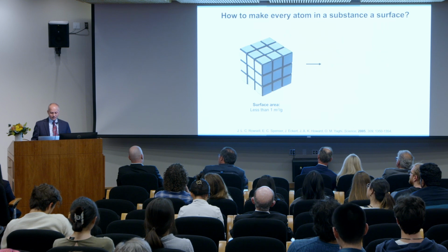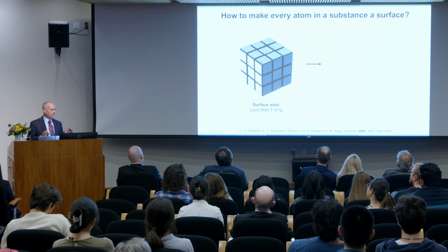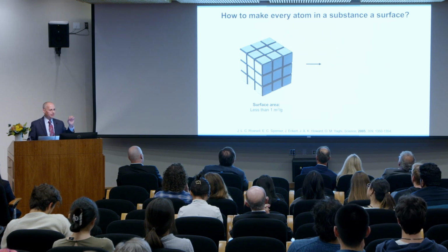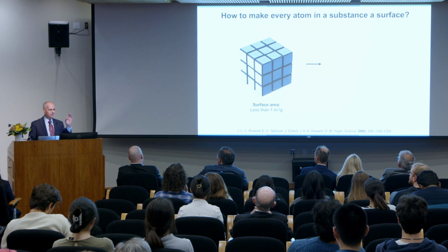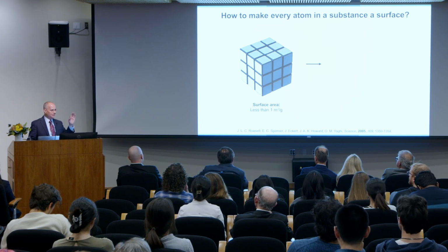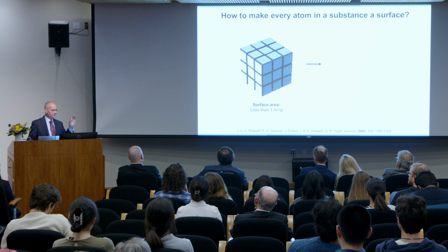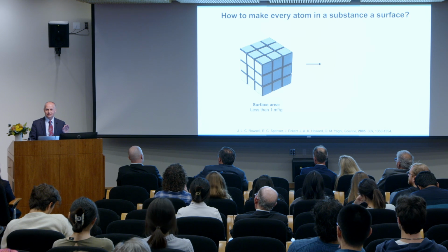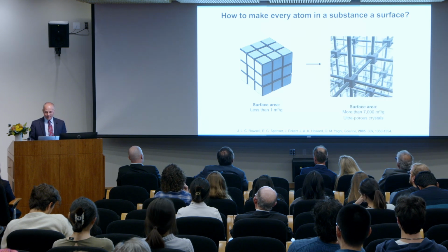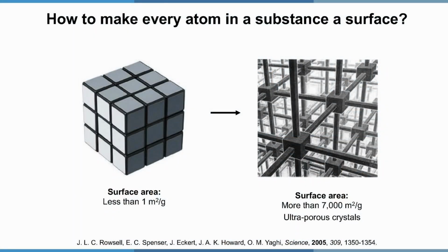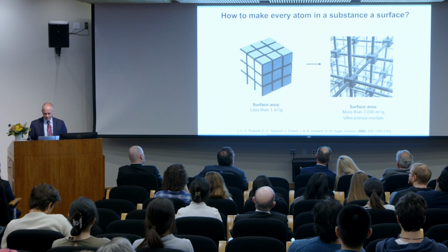So what have we done? We've taken a granular sand, basically, that has a low surface area, and we've exposed every atom, billions of atoms, and made them a surface onto which one can bind. And that's why nowadays we can achieve 7,000 square meters per gram, because we have exposed every atom in the structure, and it became an adsorptive site.